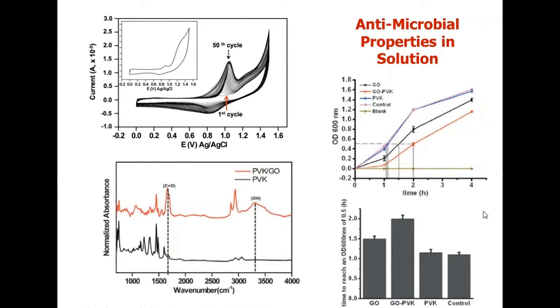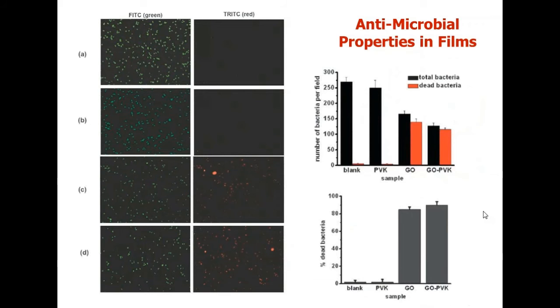So with graphene oxide, we get more dead bacteria, but more convincingly with these fluorescence imaging experiments, switching from FITC to TRITC, we have the live bacteria that is observed under microscopy present on all films. But when we finally switch to the red dye, TRITC, we get dead bacteria only present on the graphene oxide and graphene oxide PVK. We believe that this type of antimicrobial effect is a combination of reactive oxygen species generation or morphology effects based on the platy nature of the material, or even some type of quorum sensing that turns off or turns on the bacterial motility under these conditions.